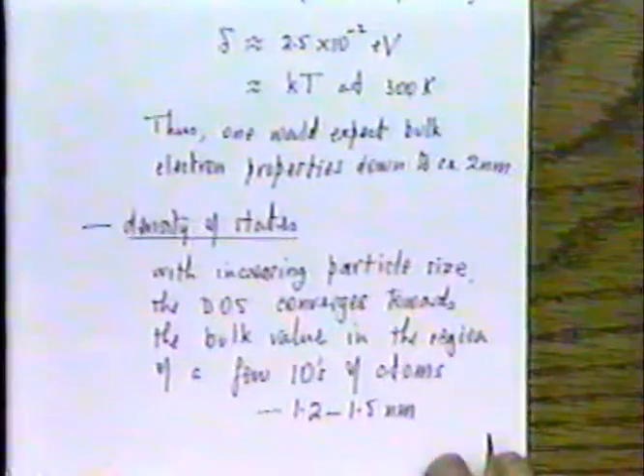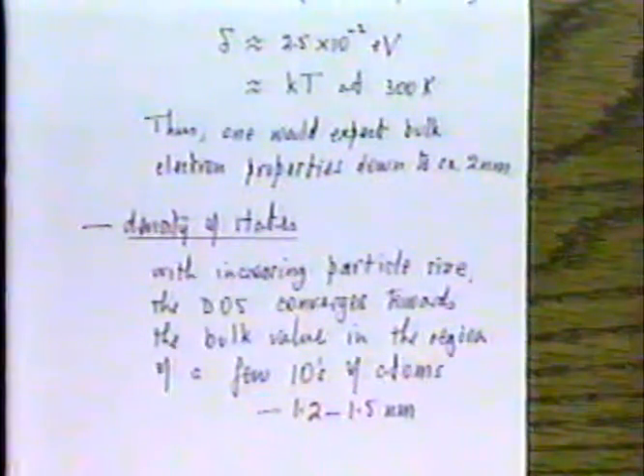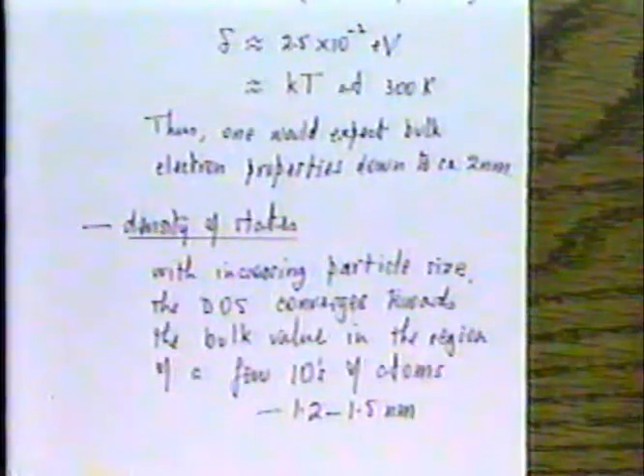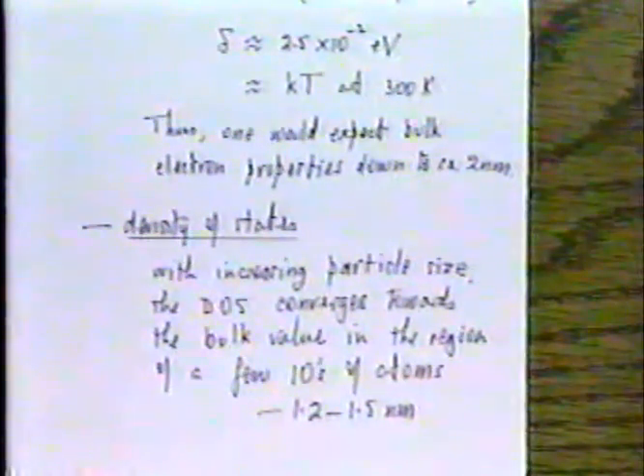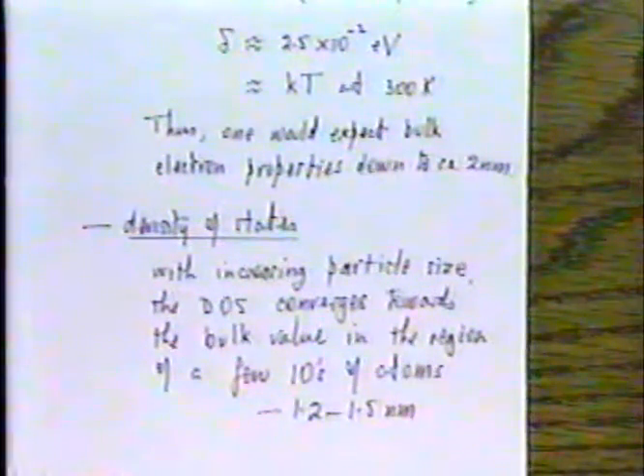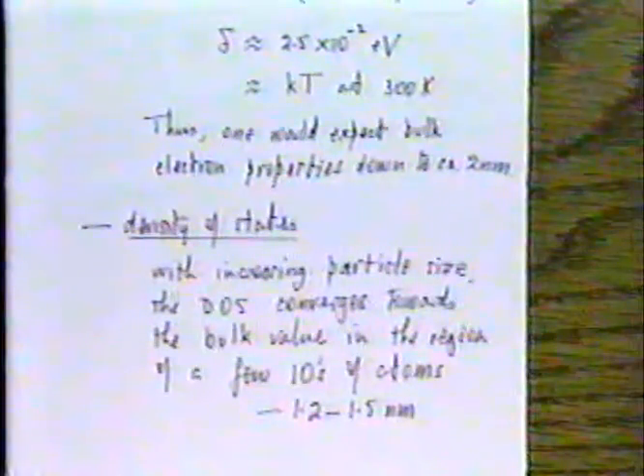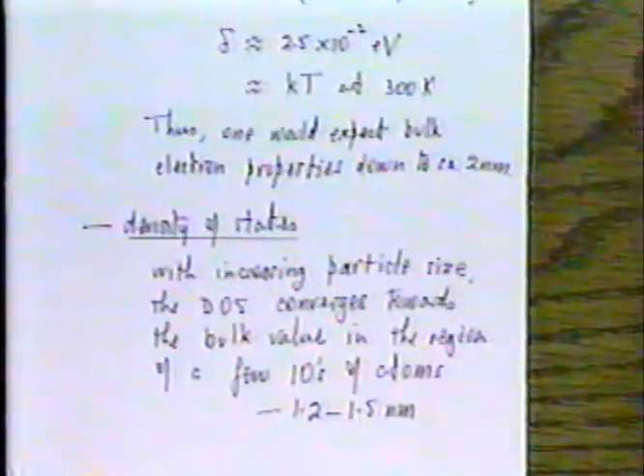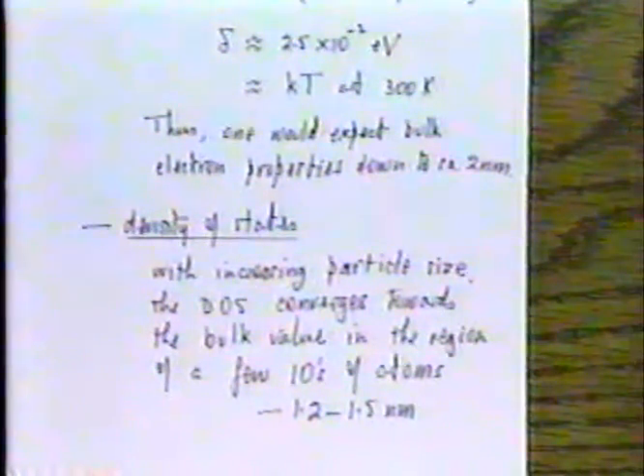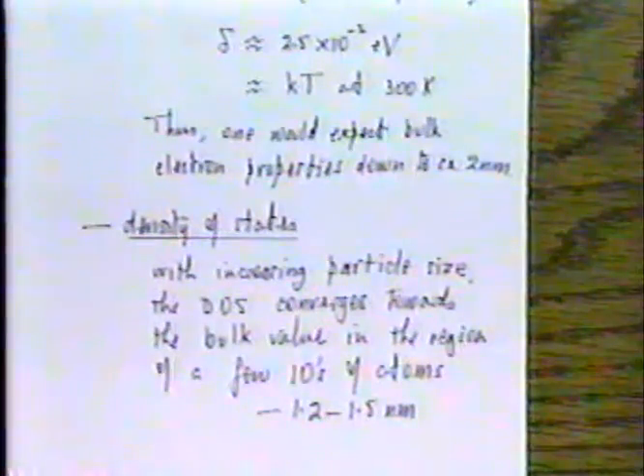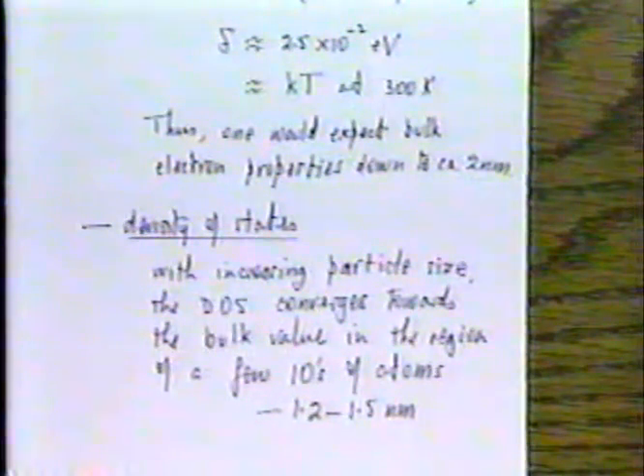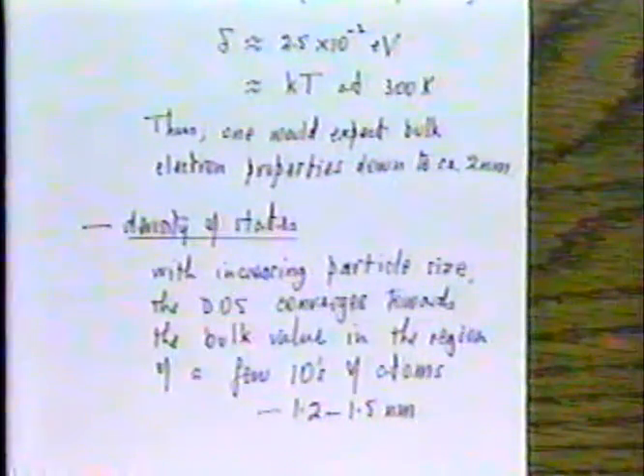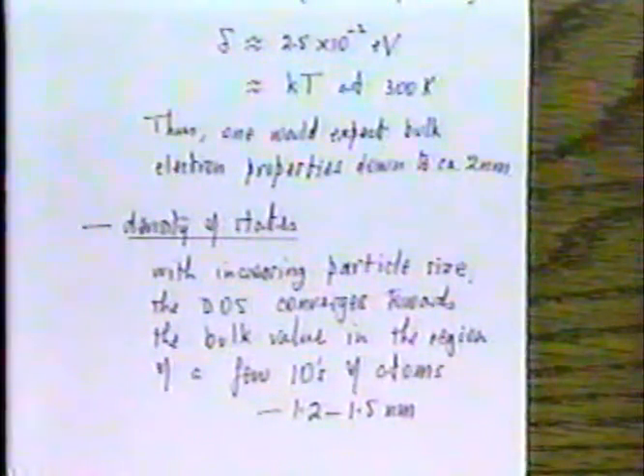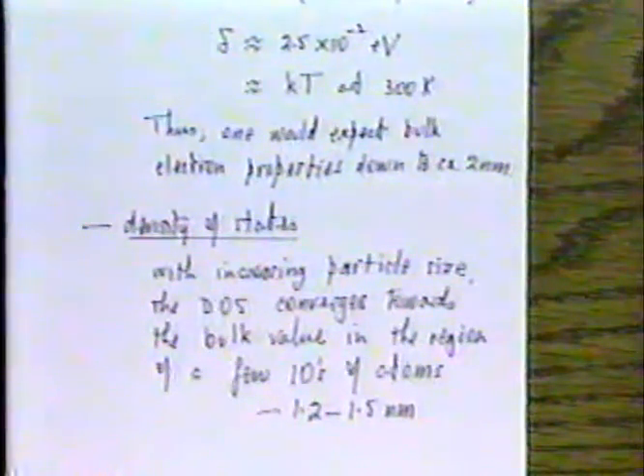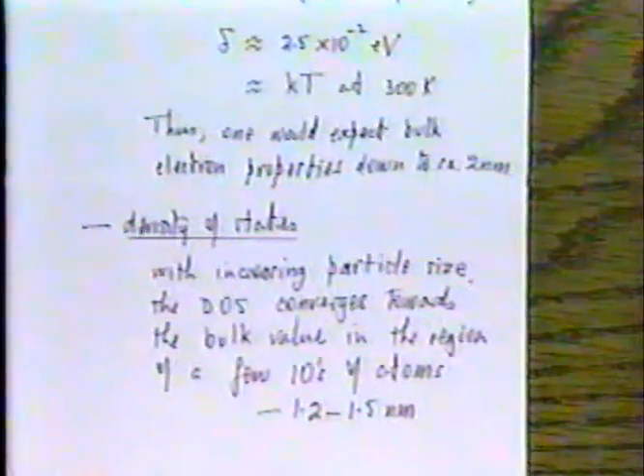There has in recent years, in fact, been a fair amount of work of a more sophisticated type dealing with the density of states as a function of particle size. And for our purpose, it's just useful to note that the density of states for small particles converges towards the bulk density of states when particles have sizes in excess of a few tens of atoms, which is, say, 1.2, 1.5 nanometers, which, for our purpose, we can say is in reasonable agreement with the result we obtained from this collective electron model, which I described to you a moment ago.